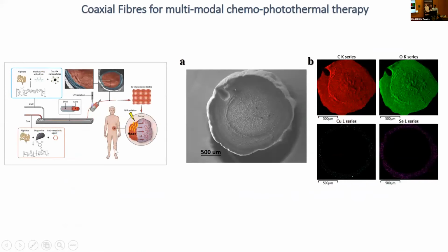Then, based on the results that we got, since doxorubicin was released in a prolonged manner, what we did next was use the same approach. Instead, this time in the shell section of these fibers, we used copper selenide nanoparticles that have photothermal properties. Basically, when you shine a near-infrared laser on them, they generate heat. So we made these core shell fibers, and we did the EDX mapping on them, and you can see the nanoparticles were only present in the shell section of these fibers, which is what we designed previously.